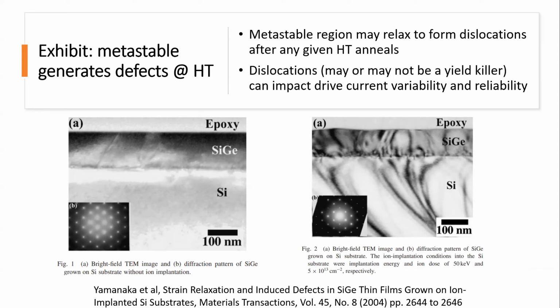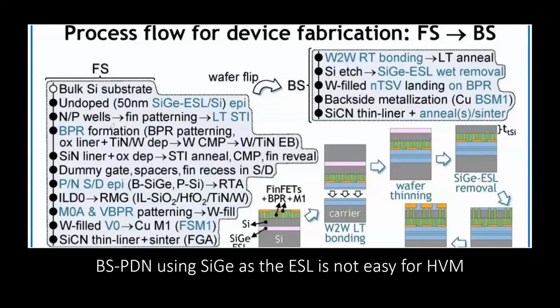And then do we have the similar process? Yeah, we do. We have the NP anneal well. We have a well, that's the implant, and then we're going to anneal back. So it does have this, and even at this step, the high temperature anneal already. Not to mention later on, you have a lot of high temperature anneal, especially the RMG process, right? The SD is pretty high as well.